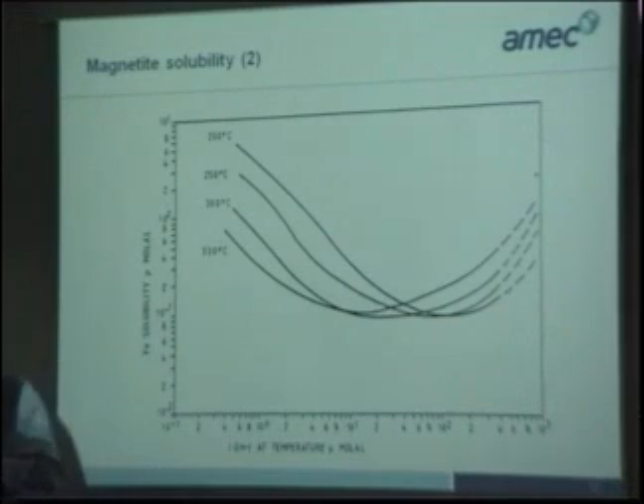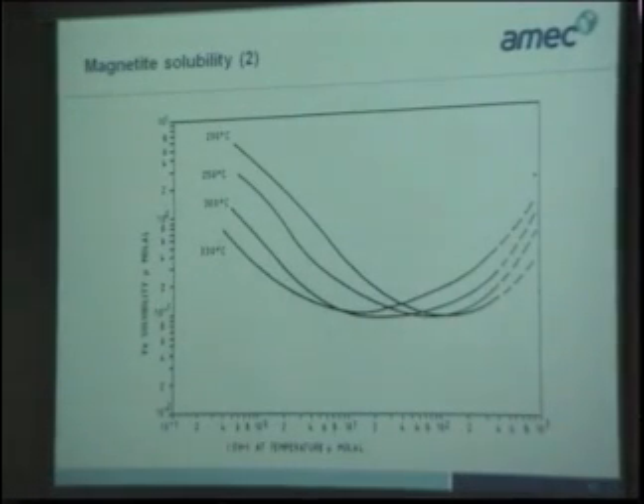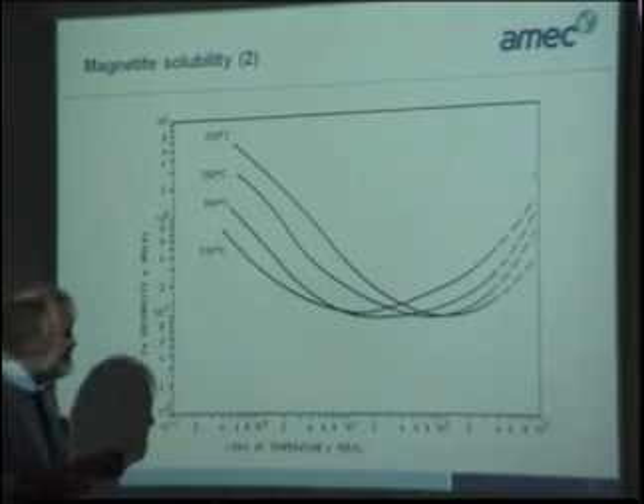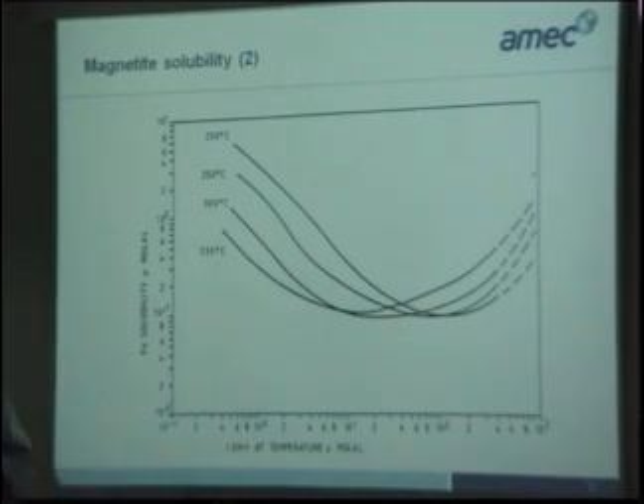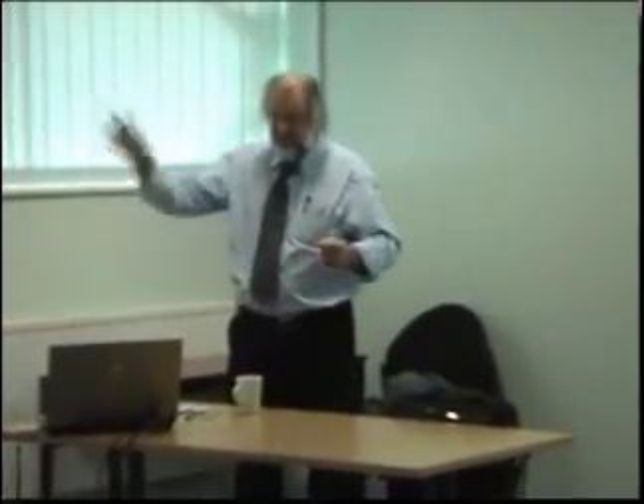Now the important thing is to mitigate against CRUD deposition, in other words, corrosion product deposition. We need to make sure that the temperature coefficient of solubility is always positive. In other words, as the temperature of the water increases through the core, the solubility of the corrosion products increases, and that will prevent to a large extent any deposition on the core. Deposition on the core is a bad thing because of the neutron flux producing cobalt-60, for example, which can then spall off and deposit itself around the circuit again.